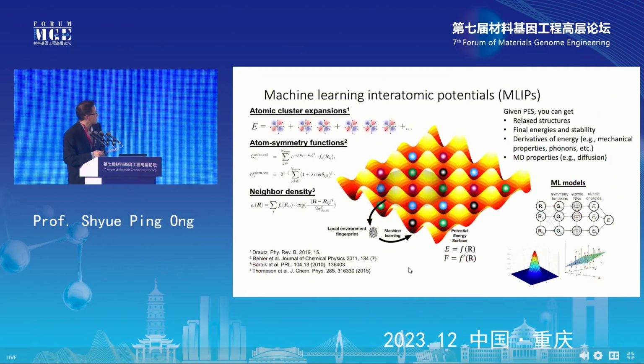All right. Now, another way in which we can relax crystal structure is to basically develop what I call machine learning interatomic potentials, okay? And this is actually one of the major success stories of machine learning in materials science, okay? By today, it is a very, very well-established approach. The way that this works in general is that you take the local environment around each atom, you then convert it into a series of local environment fingerprints, and then you use a machine learning model to map the relationship between your potential energy surface, in other words, the energy and forces on each atom, to the local environment fingerprint, okay?